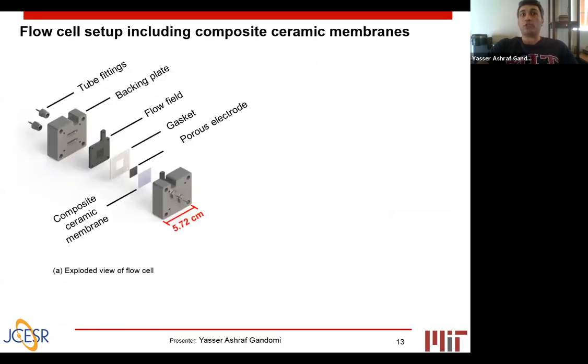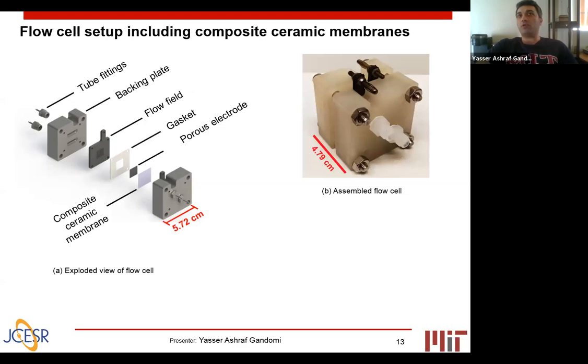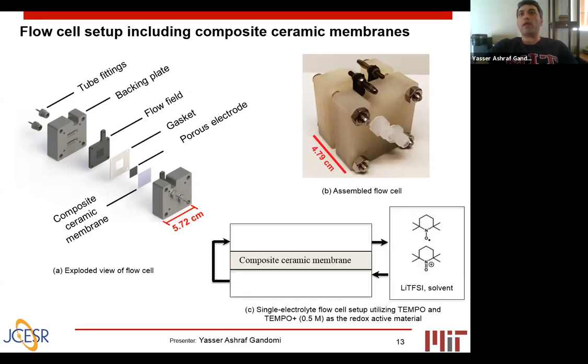So we also wanted to make sure that the performance of these membranes is superior within the flow cell architecture. This is the miniature flow cell we have designed and built in-house in our lab. So we use composite ceramic membranes within this structure using porous electrodes and flow field. And at the top right, you see the assembled version of our miniature flow fields. And I also use this flow field within a single electrolyte apparatus using Tempo and Tempo Plus as the electroactive species and LiTFSI and different solvents. I use single electrolyte structures to maintain a constant state of charge throughout the experiments.